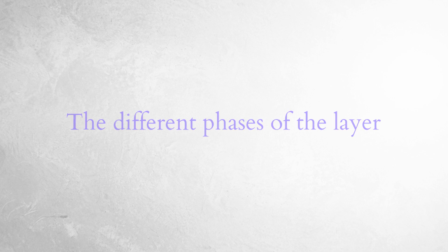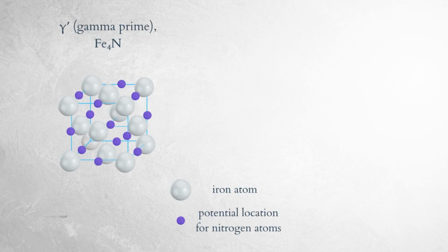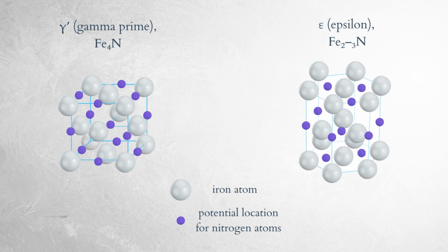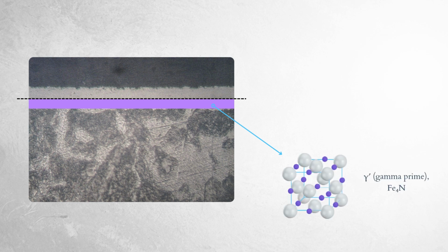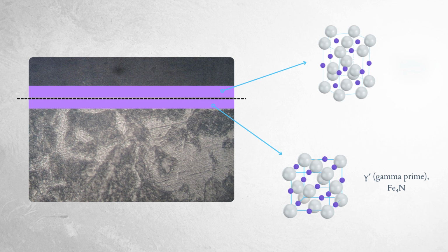In steel nitriding, the compound layer is mainly made of two iron nitride phases. The gamma prime phase usually forms at lower to moderate nitrogen potential activity. It has a cubic crystal structure. And epsilon: this phase forms at higher nitrogen potential activity, and it has a hexagonal crystal structure. A commonly observed sequence is that gamma prime forms first, and as the nitrogen activity at the surface increases, epsilon becomes more prominent.